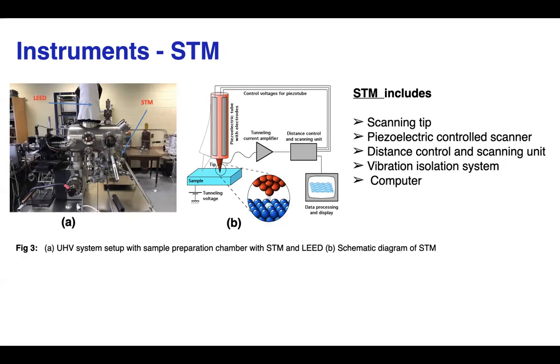The main purpose of having LEED on the system is that before we take the measurement in STM, we can check the crystallinity of the surface using LEED, because it takes only a little time to get that done. To maintain low pressure inside the UHV chamber, in this system we have 2 ion pumps and 1 turbo pump.